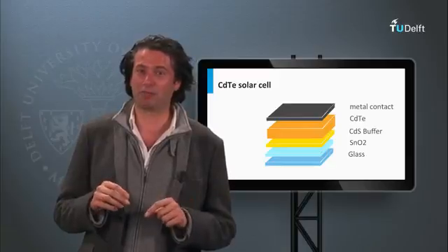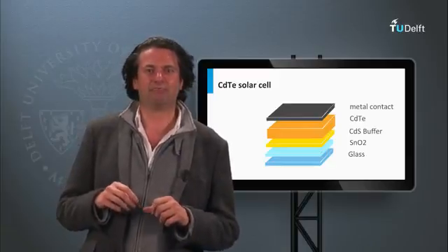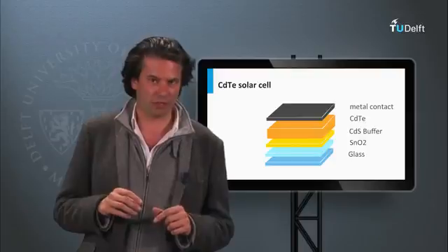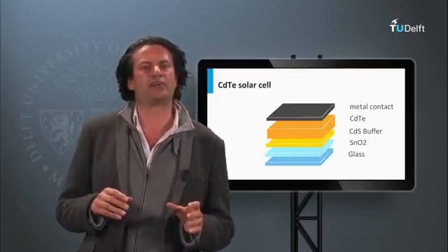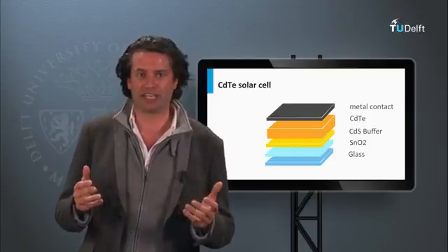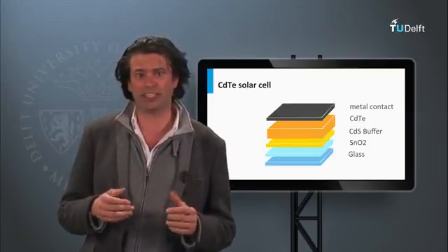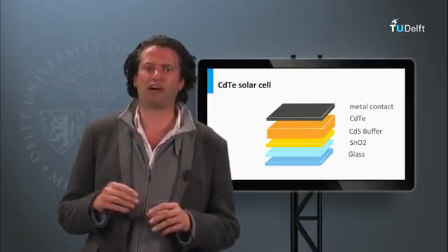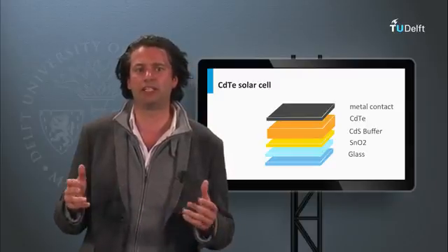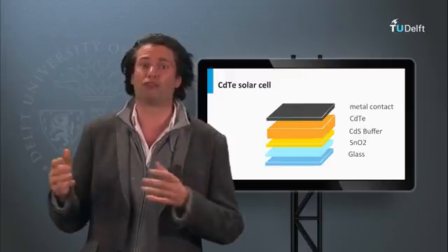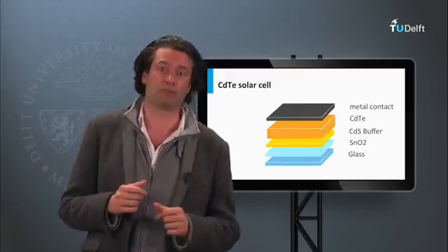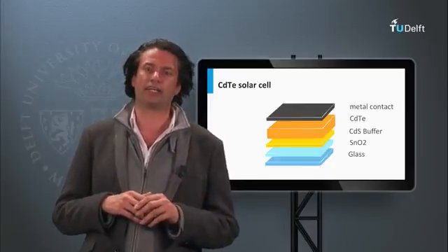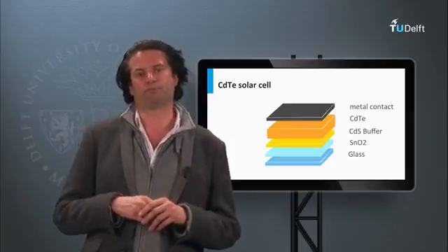Making a good back contact on cadmium telluride is rather challenging. The material properties of cadmium telluride do not allow a large choice of acceptable metals. Heavily doping the contact area with a semiconductor material improves the contact. However, achieving high doping levels in cadmium telluride is problematic. Copper containing contacts have been used as back contacts. However, on long time scales they may face instability problems due to the diffusion of copper through the cadmium telluride layer up to the cadmium sulfide buffer layer. Nowadays, a stable antimony telluride layer in combination with molybdenum is used.